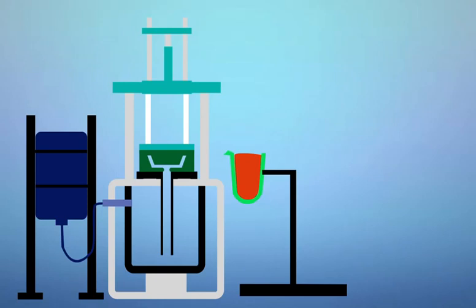The die mold is first prepared by coating it with a refractory material that can withstand high temperatures and prevent the metal from sticking to the die. The die is preheated to a temperature that will ensure good metal flow and avoid premature solidification of the molten metal. The metal is heated to a temperature above its melting point in a furnace.